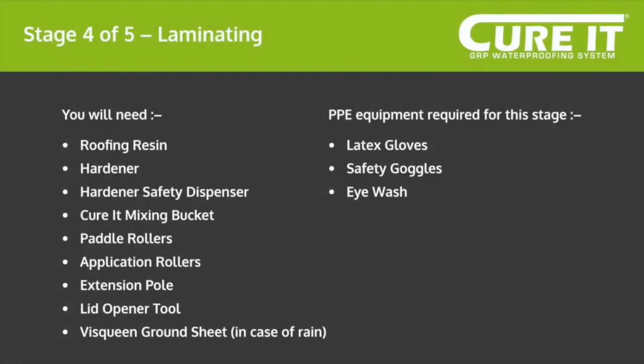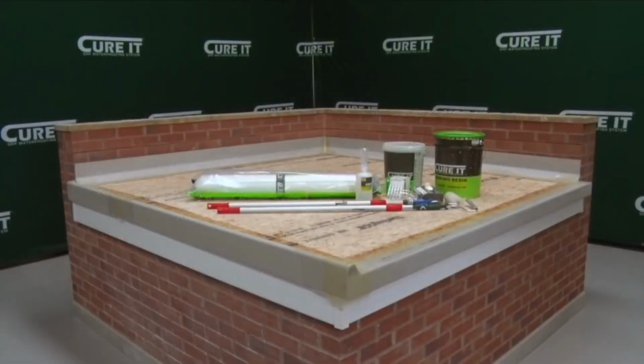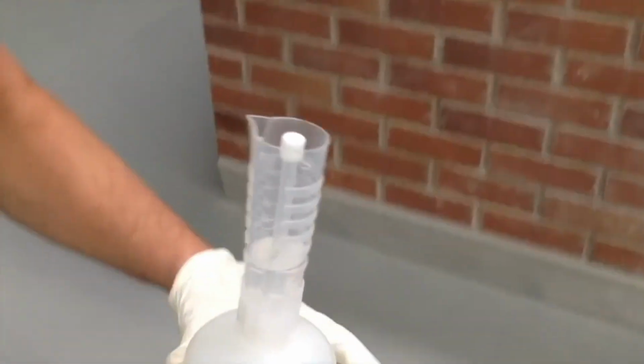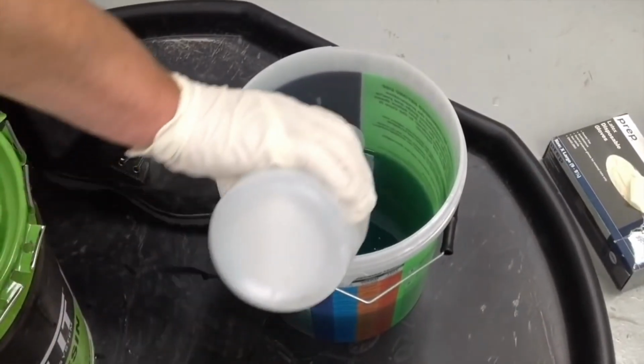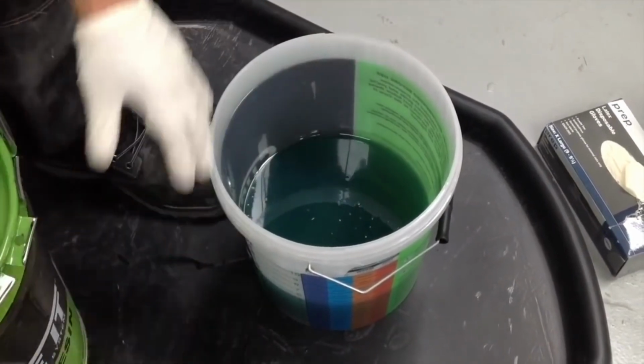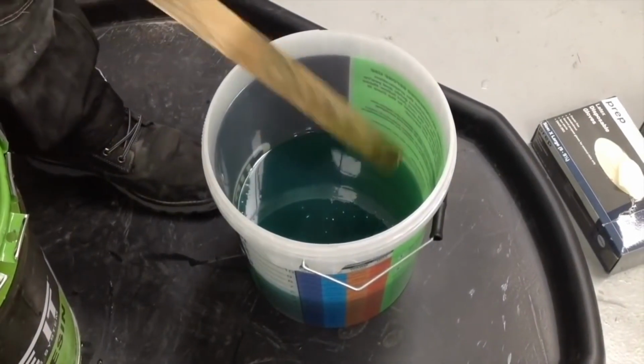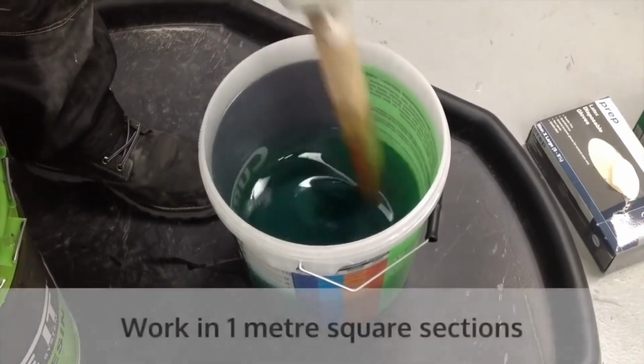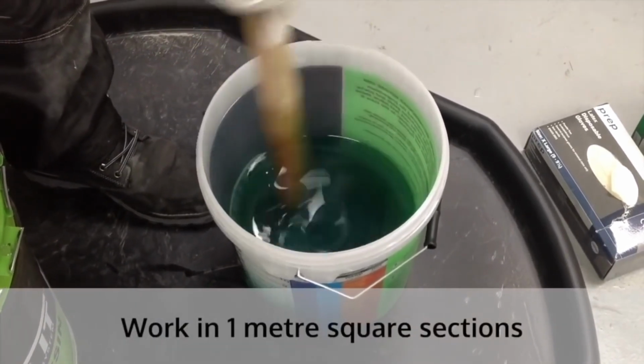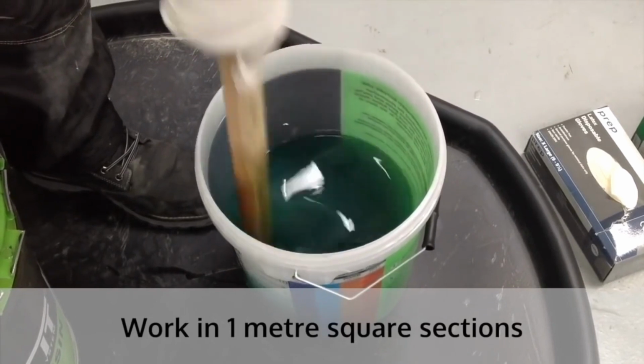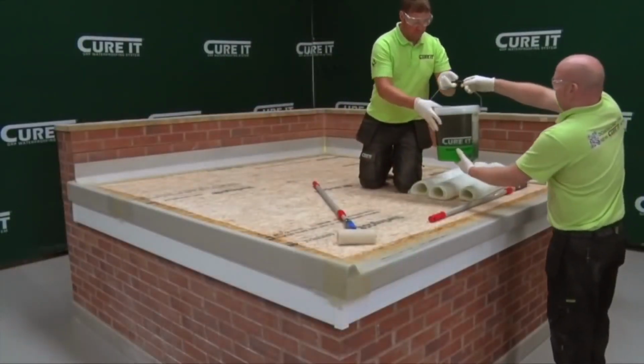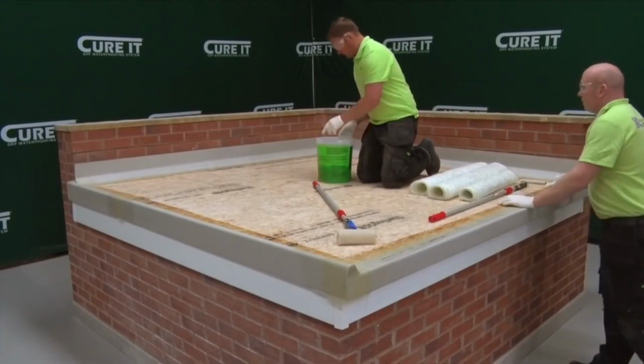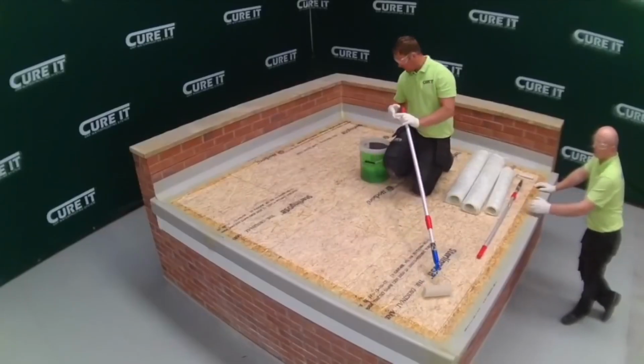Stage 4 of the installation process, laminating the main body of the roof. 2 people are required for laminating the roof, one to apply the resin and the other to consolidate the laminate. Start with a small batch of resin for the first couple of square meters, approximately 2 meters square following the hardener instructions. Work in 1 meter square sections, starting with the furthest point from the access to the roof. Ensure that the decking area is dry before laying the laminate. A wet surface can lead to delamination.